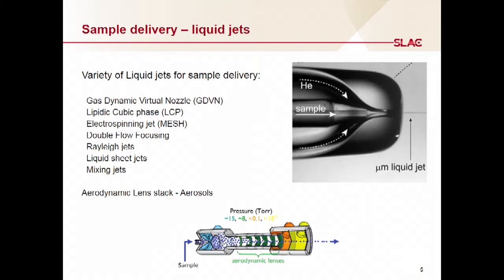And then using this high pressure helium sheath flow focusing, you can focus down to this 1 micron jet. It goes at very, very high speeds, around 10 meters per second. And so you can easily match the 120 hertz rep rate that you need. For other samples, which perhaps do not like the liquid that is here, or if you have a protein crystal